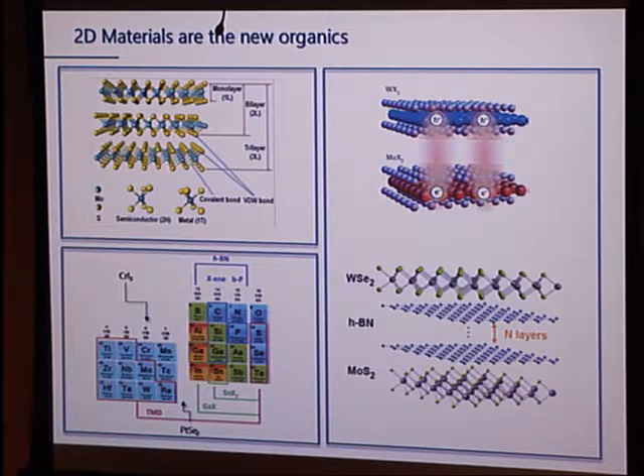You take, for example, a molybdenum disulfide, and you stack it on top of a tungsten disulfide, and you can make a stack with two, you can make a stack with more than two, and this allows you to tailor the electronic structure of these materials almost ad infinitum. And if that's not enough, then you can also change the relative orientation of these layers with respect to each other by twisting them, and this gives yet another set of degrees of freedom that you can introduce.